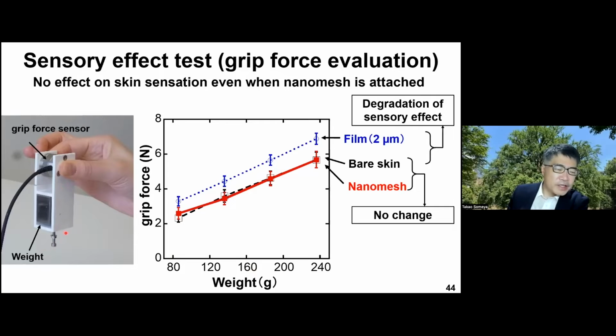We lift up some object and monitor the minimum grip pressure needed to lift this object with the fingertip covered by some materials. Indeed, when the fingertip is covered by a very thin plastic foil like 2 micron, the minimum grip pressure is slightly larger than for bare skin because skin sensation is affected by the film attachment. However, we realize the nanomesh attachment doesn't affect any skin sensation, and the bare skin and the nanomesh look identical when monitoring the grip force.